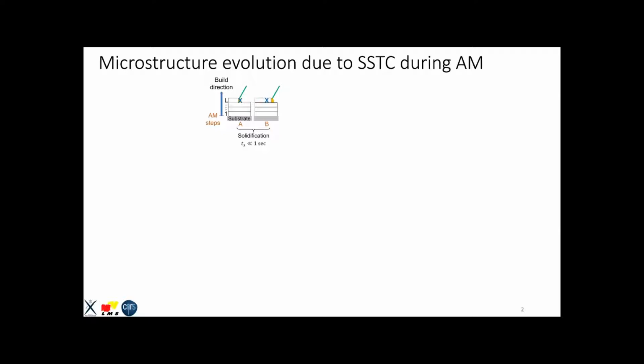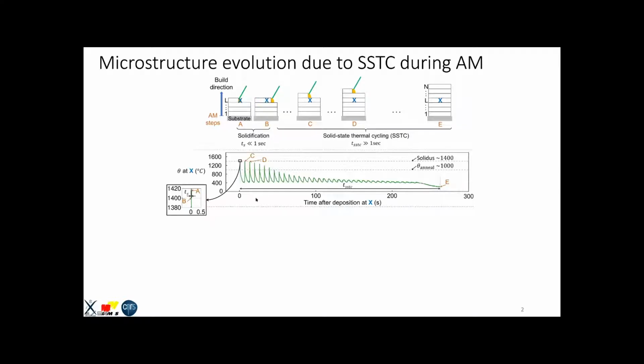Okay, so to understand what is solid state thermal cycling, let's just take an example of deposition of a wall, and we focus on the thermal history that is experienced by a point X, as you can see here on the screen. Just after deposition, it solidifies rapidly in a few milliseconds. And then for the rest of the build cycle, it is subjected to thermal cycling in the solid state. Now, this thermal cycling occurs over a very long period of time at different temperature amplitudes and rates.